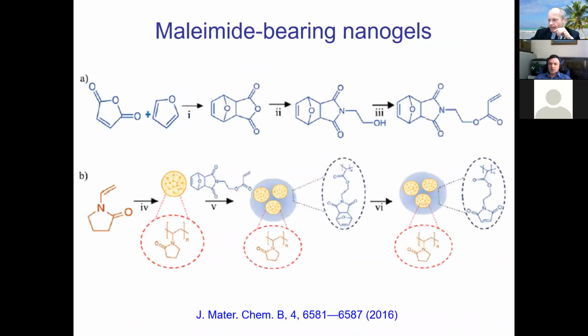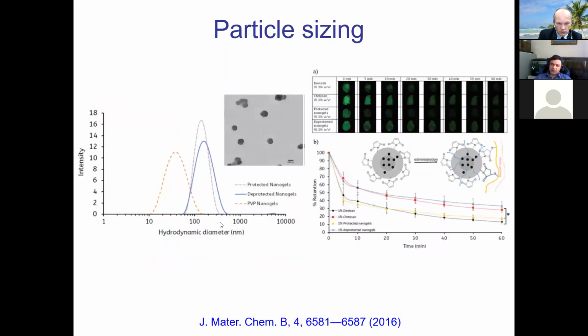In our first study, we used a rather complex series of transformations to arrive at a maleimide-containing monomer that was protected. We then used that monomer on the surface of polyvinylpyrrolidone nanogels, which we synthesized by conventional free radical polymerization. Then we post-polymerized the maleimide-containing monomer on the surface. We ended up with particles that had several cores of PVP, but were evenly coated with the maleimide monomer, which was then subsequently deprotected. And then we used it in our studies. This slide demonstrates an example of what happens with protection and deprotection of this monomer, using dynamic light scattering.